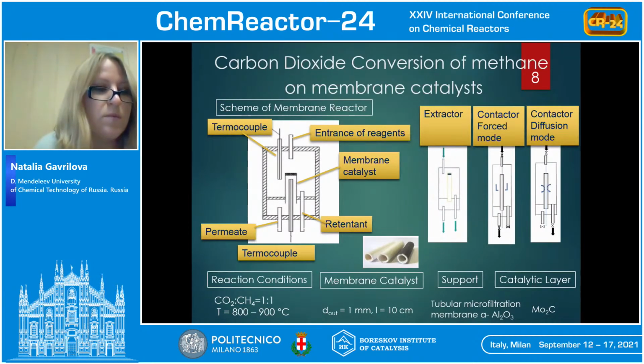In this paper, we will present the new results of a kinetic study of dry reforming of methane in a membrane reactor contactor, which works in two different modes: forced mode or pressure drive mode, and diffusion transport mode. In the forced transport mode, the reagent mixture passes through the pore structure of the membrane catalyst due to the pressure difference. In the diffusion transport mode, the entire mixture of reagents enters and exits from the shell side of the reactor and penetrates into the membrane catalyst as a result of concentration difference. These results will be compared to the reactor extractor. A scheme of the reactors, flows, and some reaction conditions are presented on this slide.